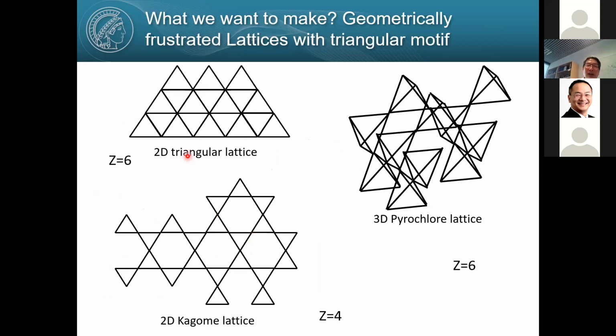Okay, so in general, we want to make that kind of lattice of spin one-half, like triangular lattice. Okay, so this has coordination number 6. And the 2D Kagome lattice, in this case you have only 1, 2, 3, 4 coordination. Okay, so much smaller than triangular lattice. So therefore we might have a much better chance for Kagome to find quantum spin liquid. Well, we may go even 3D. If we have the so-called pyrochlore lattice, corner-shared tetrahedra. Okay, so you have 6 bonds like a triangular lattice. So though it's higher dimension, the coordination number is the same as 2D triangular lattice.